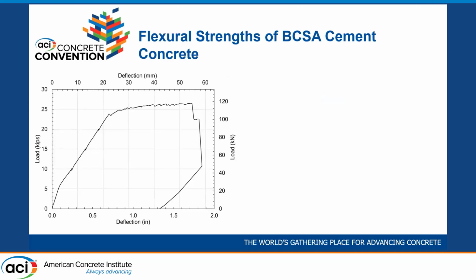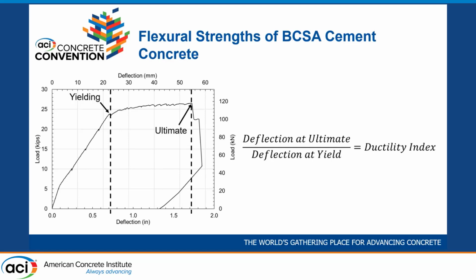So another thing we looked at is something that's known as the ductility index. It's a way of comparing beams in terms of how ductile they are. So what we do is we look at the yielding and the ultimate point on the beam's load versus deflection curve. The distance between these is kind of an indicator of ductility. We want more space between these 2 values. So we take the deflection at ultimate and the deflection at yield, and the ratio of those 2 numbers is the ductility index. So a bigger number here is good. It means more ductility, more warning before a failure or before the concrete crushes.